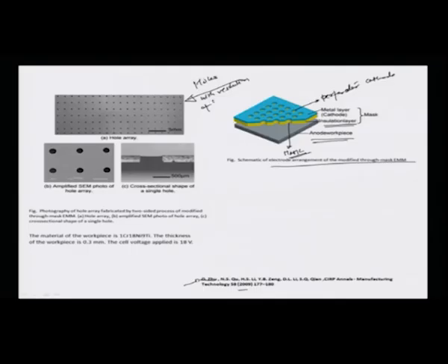Close to about probably 0.5 mm. Each of these holes must be in the range of a few hundred microns, I am sure, and this is a blown up SEM image of the same hole array. And this right here illustrates the cross sectional shape of a single hole. So the work material in this case, which is made the anode, is a chromium alloy, 18 chromium, 9 nickel, titanium. The thickness of the workpiece is about 0.3 millimeters, that is about 300 microns. Okay, and the cell voltage that you are applying to do this machining here is 18 volts.